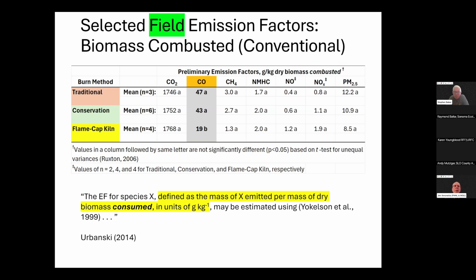So now this is what I would call the conventional emission factors, and these are very similar to what Steve showed. They're based on what he showed. But what we did was a different statistical analysis to distinguish between what was significant and what was not, just here for the major components emitted. And you can see basically the only thing showing as being significant are the carbon monoxide values.